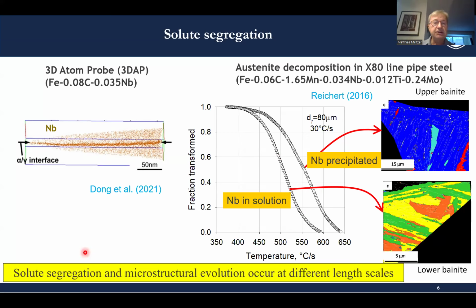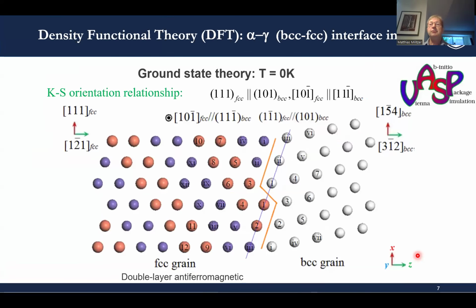What we have to realize, of course, is that solute segregation on a nanometer scale is a very different length scale from the microstructure evolution, where we are on a micrometer scale. So what can we do to address these different length scales? We can first do atomistic scale simulation, and the starting point is increasingly ab initio density functional theory. An example is shown here for an alpha-gamma interface in iron. The typical code that people now use is VASP, the Vienna Ab initio Simulation Package, probably the most advanced code in the DFT calculation area.